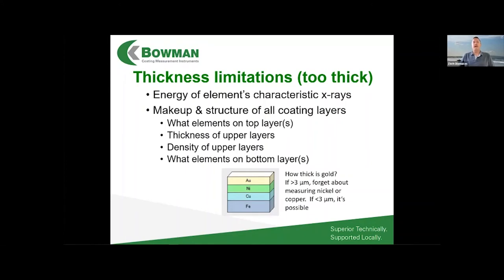To limit us, if something is too thick, it depends on the makeup of those different layers. I've got a picture here of gold plated over nickel, over copper, over iron or steel. If I needed to measure the nickel and the copper underneath the gold, I have to know how thick that gold is going to get. I know from experience that if the gold is more than about 3 microns thick, you can forget about measuring anything underneath it, because gold is very dense. The atoms are very large compared to something like nickel or copper, and those weaker nickel and copper X-rays just aren't going to penetrate through that gold for very long distance. If it's less than 3 microns, then we've got a good chance of measuring the sub layers.